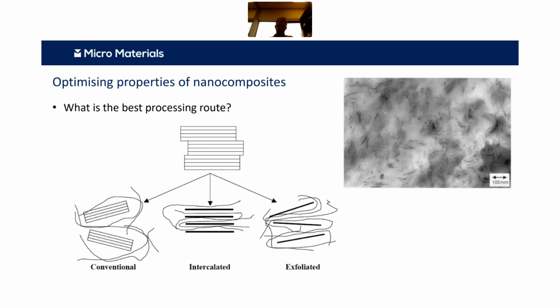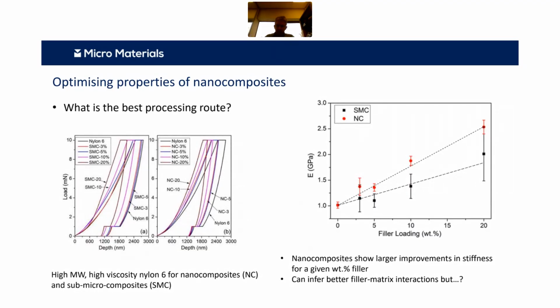If you intercalate, you can increase the gallery distance within the clays, and then you can put polymer chains within there. That's quite a good strategy, and in practice you get even bigger improvements for exfoliated structures. So a lot of polymer and composite design is based around trying to optimize for these intercalated and exfoliated structures. We have an example here, again from quite a while ago, where there is a nylon 6